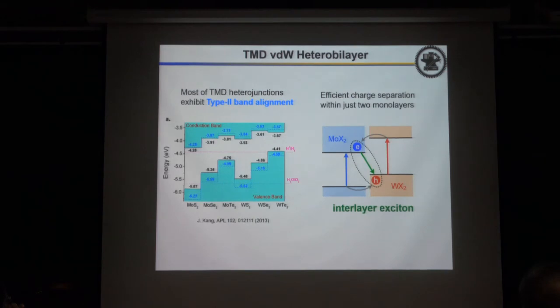So if you stack two different TMD materials together, typically this kind of material has so-called type 2 band alignment, like this. This is one material band gap, and this is another band gap. And then they have this so-called type 2 band alignment. That means that if you have electron and hole in the two materials, electron will transfer to one layer, and the hole will go to another layer. So electron and hole will separate at two different layers in this case. So we call this so-called interlayer exciton.